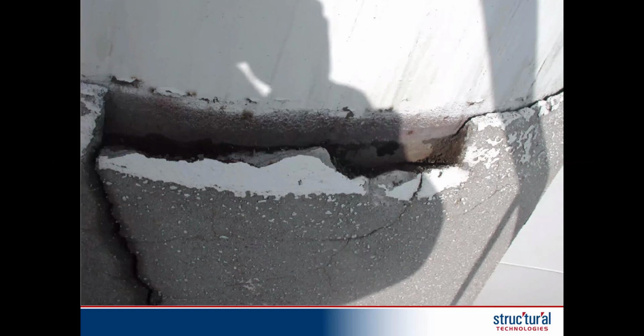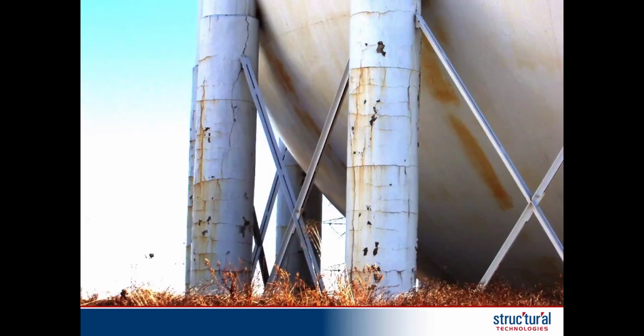So we knew we had to remove that section or put a new rain gutter, which goes all the way around the member to keep rainwater from going down into that annulus. When we look at these structures, you can see that with fireproofing, many times the diagonal members don't have to be fireproofed, so you can see that readily there. They're not fireproofed, but you can see the amount of damage in the pipe columns here, especially with the corrosion emerging from a lot of the cracking.